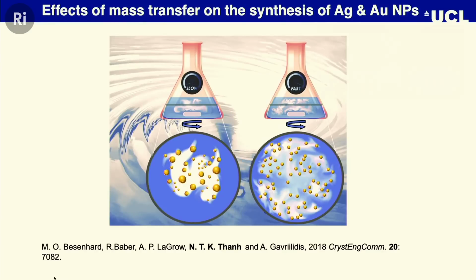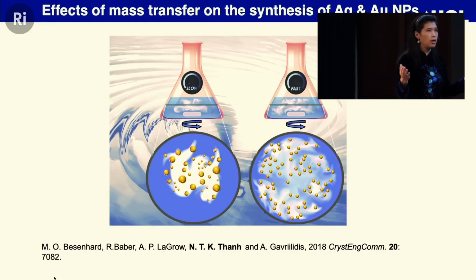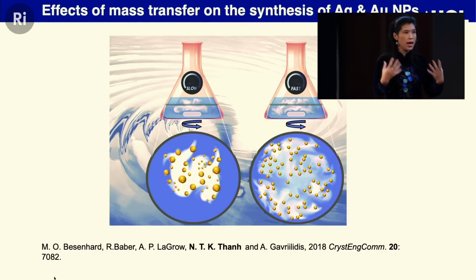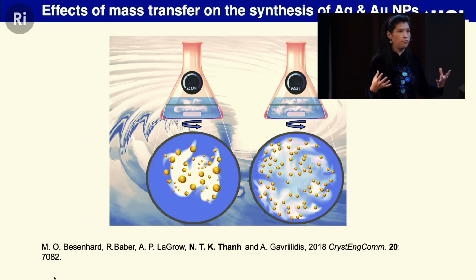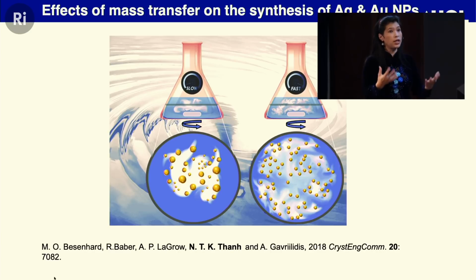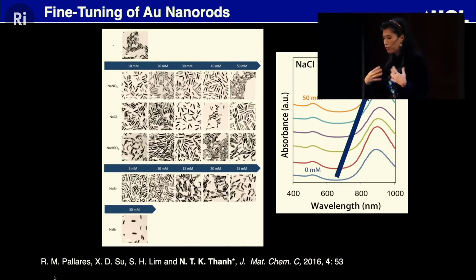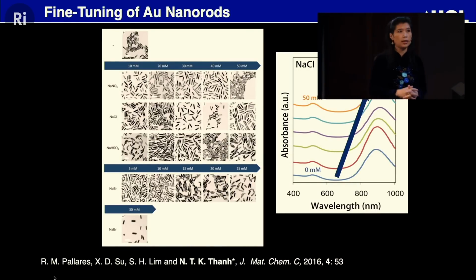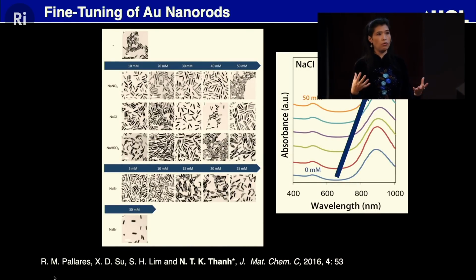So when you do the synthesis reaction, you can stir, and you're not aware that by stirring slow or fast, you may change the mass transfer. That means how the material comes together to form nanoparticles, and the particles could be polydispersed or monodispersed. Okay? So then, moving on from that, we also make gold nanorods.